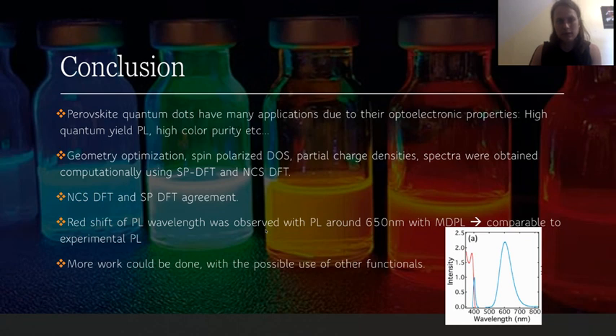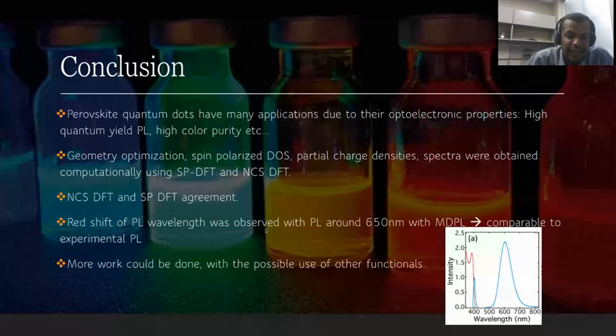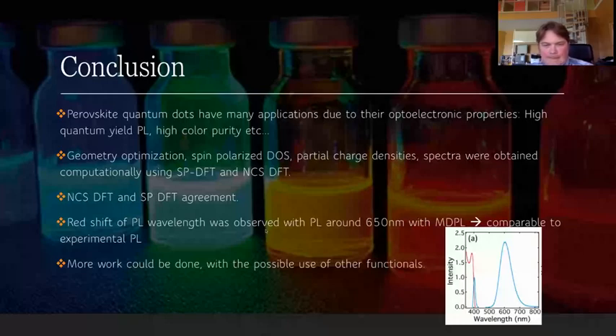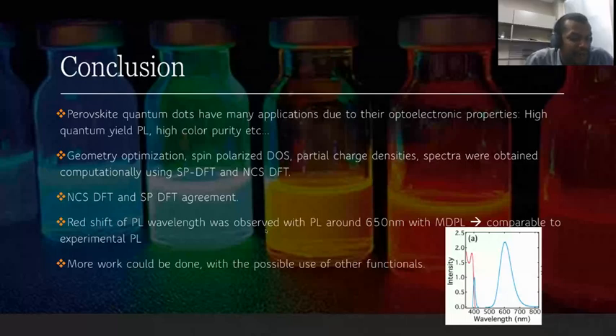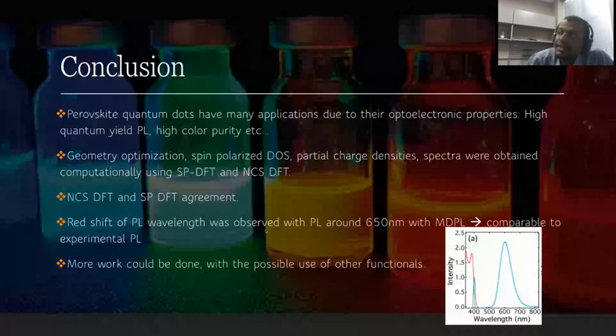The most impressive, you mean? Yeah, the one that would make a good journal cover, the main observable or main figure that you found. What I really liked were the orbitals. I really like the orbitals and how we can compare them to the ones from the manganese. But I also like the density of states, the one from the doped model, the spin polarized one, maybe the one with the non-collinear spin as well, or maybe even the PL. But the PL may be expected.